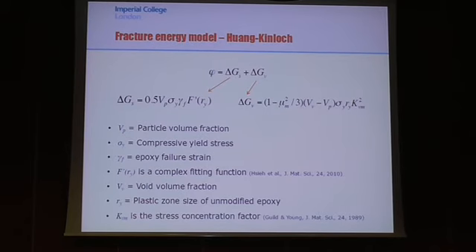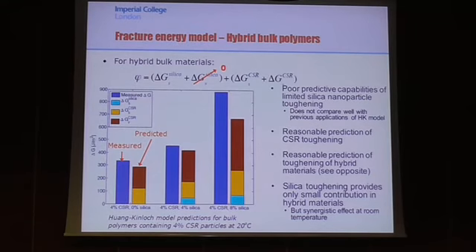This is a fitting function from Hsieh-Kinloch and later modified by Sey et al. And we can measure the void volume fraction, and we measure the plastic zone size relative to unmodified epoxy, and then the stress concentration factor, which we take. It's different depending whether it's a hard particle, soft particle, or a void. And when we have the hybrid polymers, the toughening increment can be expressed as basically the sum of the toughening due to the silica and the toughening due to the CSRs. We didn't see any void growth with the silica, so that's 0.